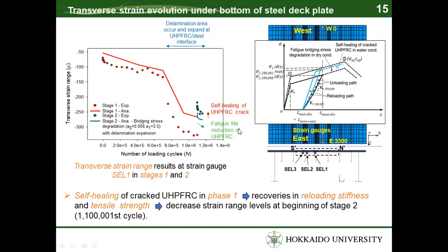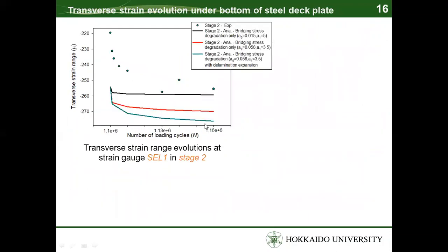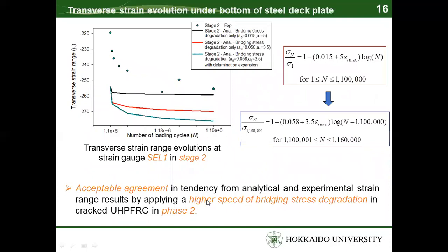After that, under moving wheel loading, due to the fatigue life reduction of UHPFRC, an increasing tendency of transverse strain range at this location can be observed. In this phase 2 of the material model of UHPFRC, by applying a higher speed of bridging stress degradation in UHPFRC, an acceptable agreement in tendency between analytical and experimental strain range results could be obtained, especially for the early cycles of this stage.